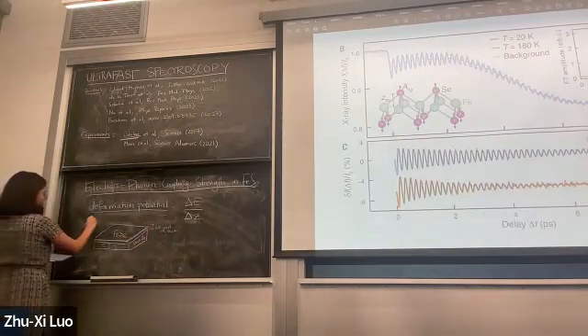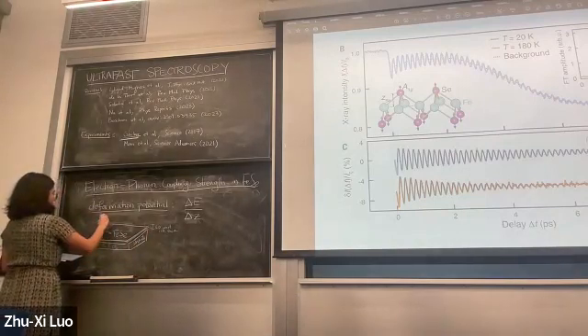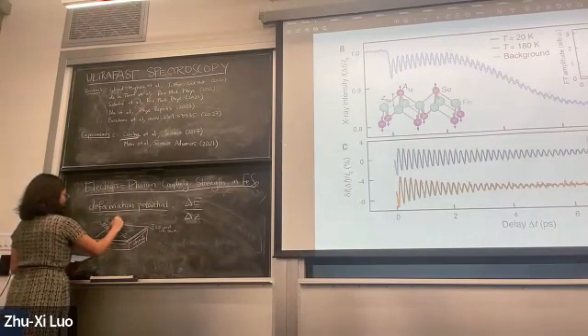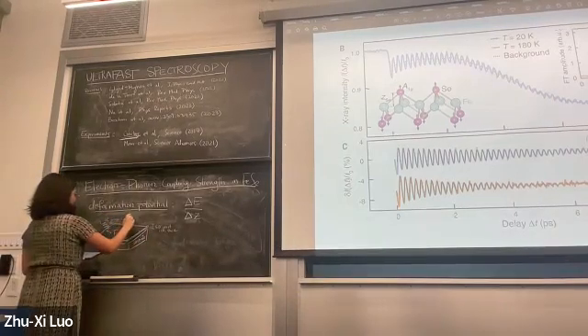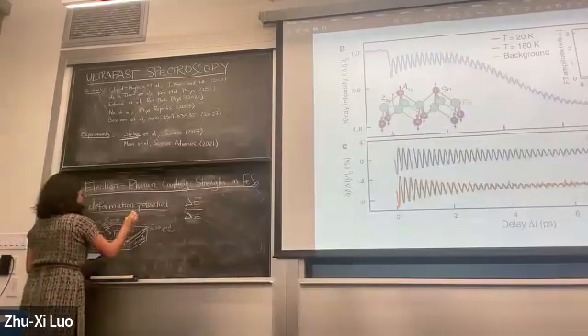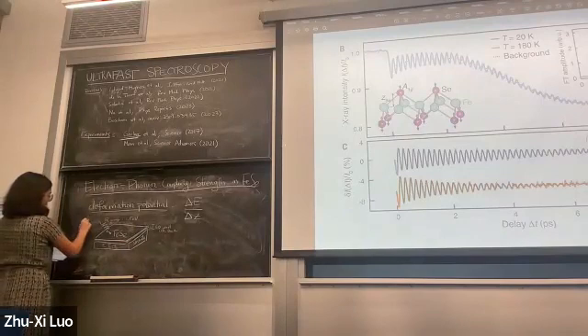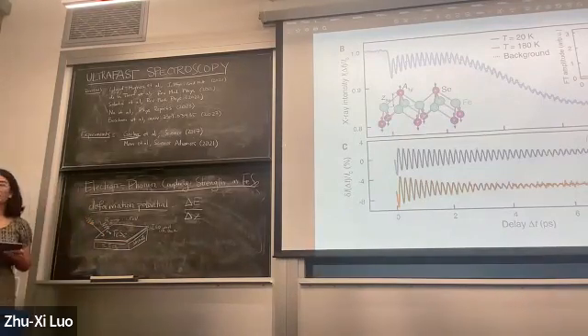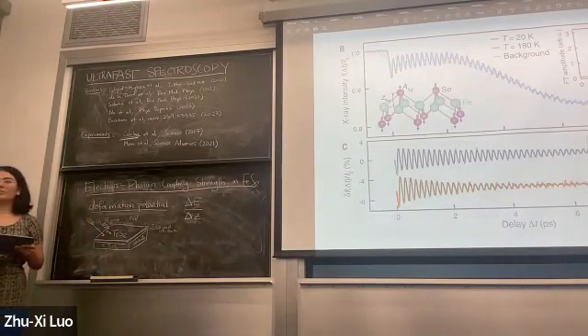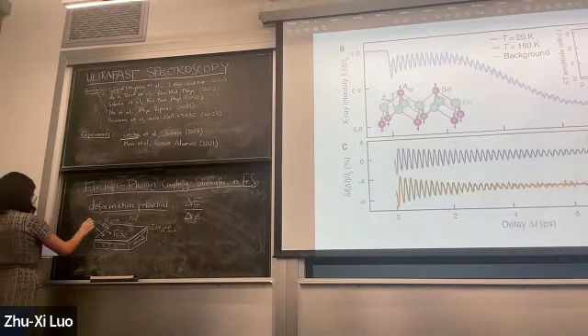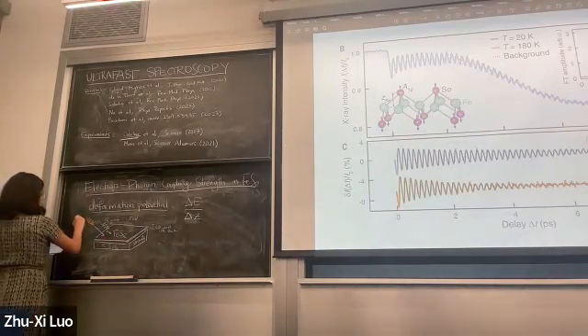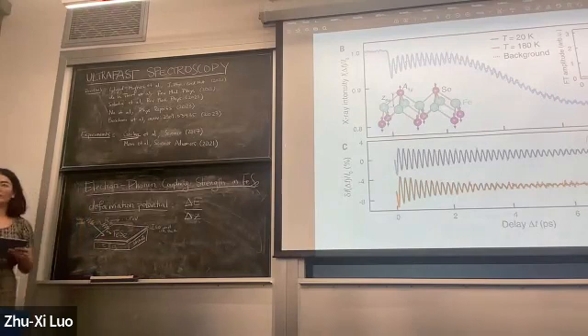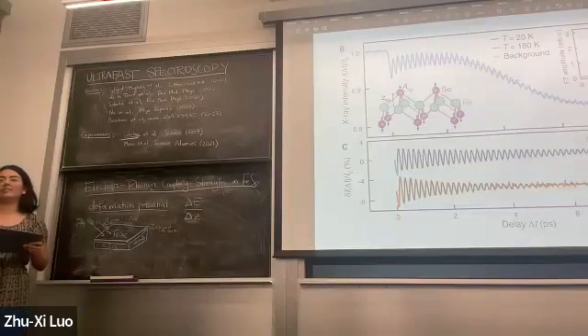And again, we're going to send in some IR pump. Specifically, the peak energy is 1.5 electron volts. And then in this case, we're going to be using two different probes. So first, we're going to be using an X-ray probe in an X-ray diffraction experiment to look at the dynamics of the lattice, to actually directly look at the phonon excitation.